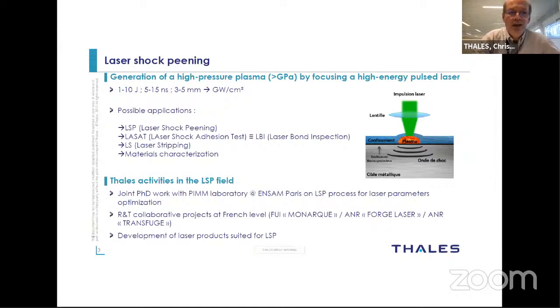The pressure coming with the shock wave is quite high. We talk about gigapascals, and the typical laser energy is joules or fractions of a joule, up to 10 joules. Right now the state of the art is mostly in near infrared, 1064 or 1053. The pulse range is typically between 5 to 15 nanoseconds, and the spot size is typically 3 to 5 millimeters, could be more, but basically you are generating an intensity on the place to process that is several gigawatts per square centimeter.